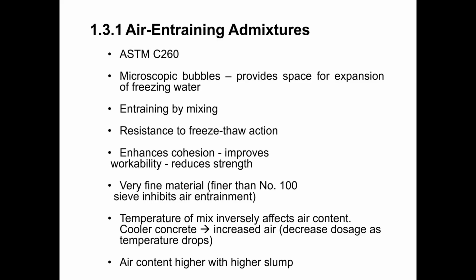Keep in mind that very fine material in your sand, and when I say very fine material, I mean material finer than the number 100 sieve, that can affect the formation of these microscopic air bubbles within the matrix of the concrete. So if you're using a coarse aggregate that is dusty or a fine aggregate that has a very fine gradation, then you may end up having to use more air entraining admixture than you would otherwise need to use just in order to achieve the desired level of air entrainment.